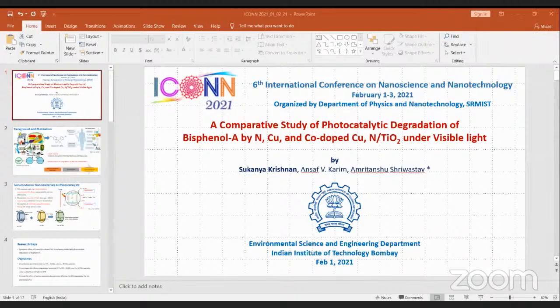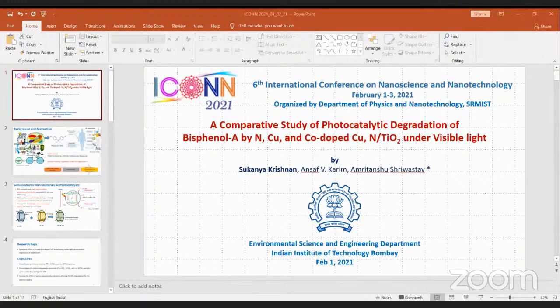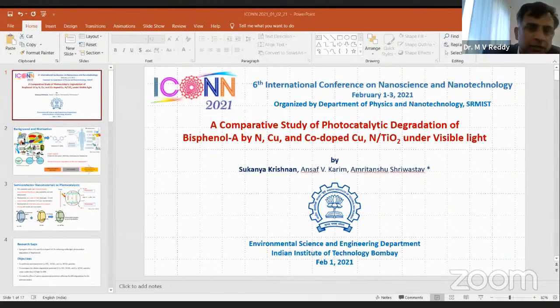And also, did you see any color change with the nitrogen doped TiO2? Yes, sir. Nitrogen doped was pale yellow in color, and the co-doped one is green in color. Okay, yeah, that is normal. So you have to check that. And if I remember RSC Advances 2012, you can look up my name. A lot of doping has been tried with a simple molten salt approach. You don't need any expensive salt. Just put it in an aluminum crucible, put titanium sulfate, that way. I think that is the work I did long back. So better please refer. Sure, sir.